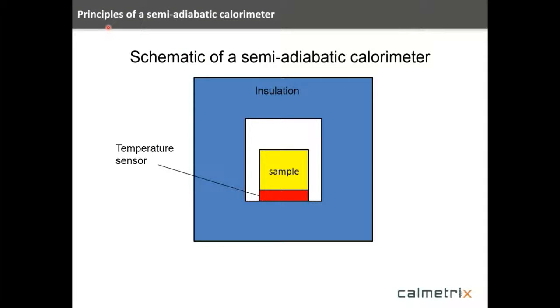Now let's turn our attention to the principles of a semi-adiabatic calorimeter, the second type of instrument that we supply into this industry. And this is a schematic of that type of calorimeter. Again, we'll start on the inside. Here it's much simpler. We basically have a sample location, which sits on top of a temperature sensor in this case, and then that entire assembly sits inside of an insulated chamber. So basically here we're monitoring the temperature in the sample as the cure goes forward. So there's a temperature rise, as you know, and that's what we're measuring in the semi-adiabatic.